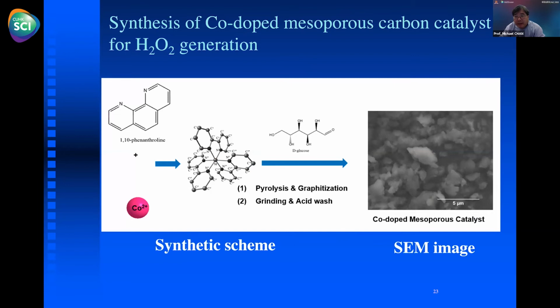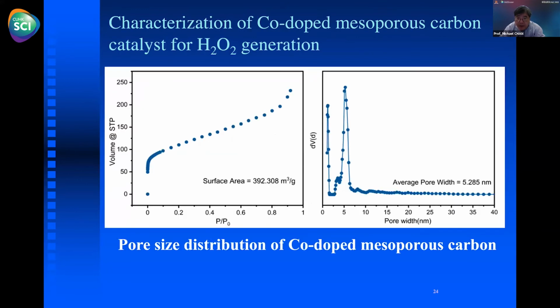So then she had to make the electrode that's going to be used to make the H2O2. They developed a method to make a cobalt mesoporous carbon catalyst. They take 1,10-phenanthroline, make a cobalt complex of it, and then they pyrolyze that cobalt complex in the presence of glucose, and then do some grinding and acid wash to make a porous carbon surface with some cobalt sites. And here's an SEM picture of that catalyst. This catalyst has a surface area of about 392 meters squared per gram, and it has an average pore width of about 5.285 nanometers, meaning that the oxygen can get in and out of that electrode.